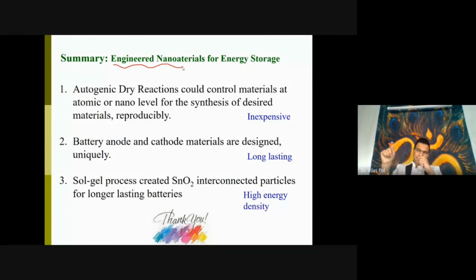So we started heating those particles to higher temperature. So the surface area went down because particles got sintered to each other. Namely, if I have a 10 nanometer particle and another 10 nanometer particle is connecting to that, some of the surface area is lost. But at the same time, there was a reorganization in the particle because of the sintering. So particles came together, but then because of the movement and sintering, there is a cavity. And that cavity was the important thing for us.